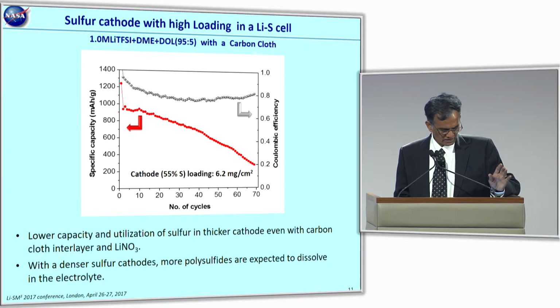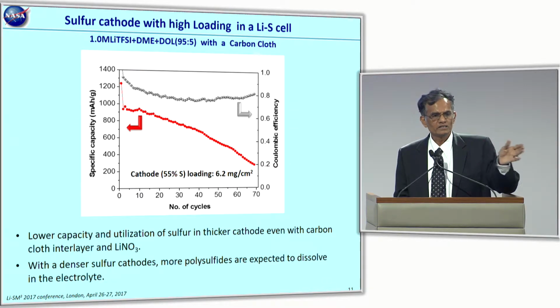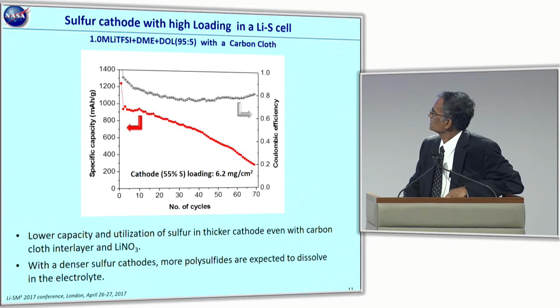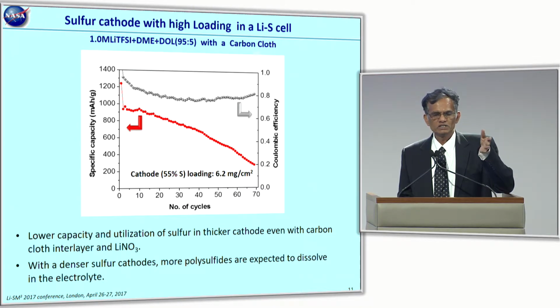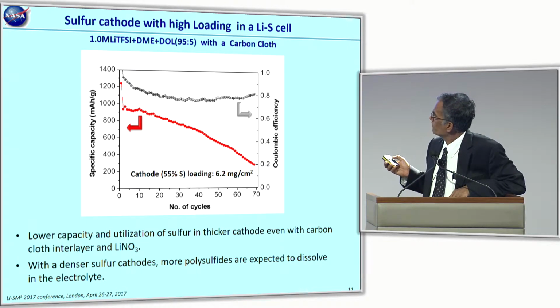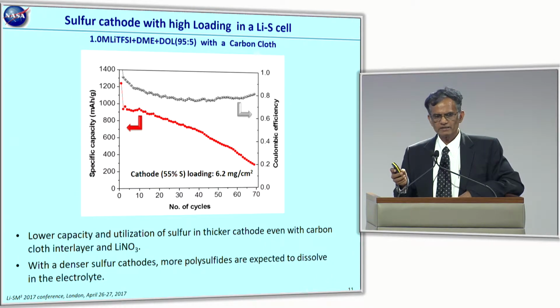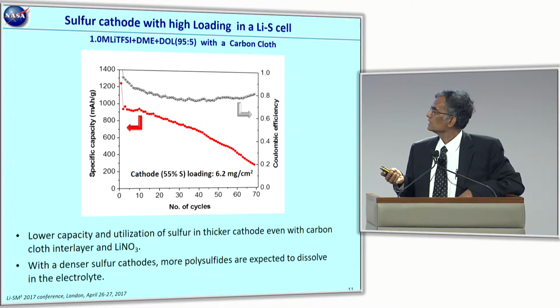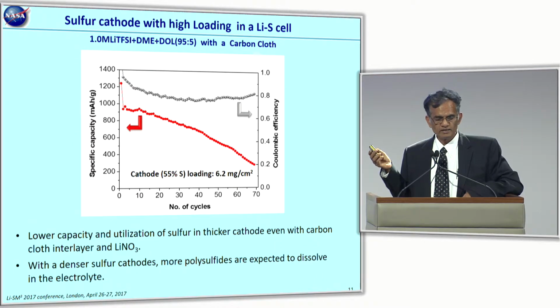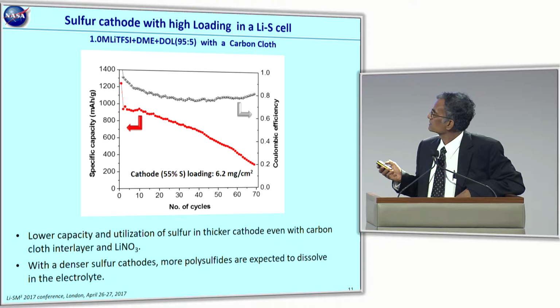And then we determined that we stuck to a carbon interlayer. This is based on the reports from Manthiram, UT Austin. We realized that the presence of a carbon layer between the separator and the cathode seemed to provide us good reproducibility in terms of data. Without that, at least with the loadings that we are dealing with on the sulfur cathode, it was rather difficult to deal with this shuttle. So with a combination of this lithium nitrate and the carbon cloth, instead of a carbon paper, we used a carbon cloth, which is much easier to cut to size. And you still see the fade is not acceptable at this loading, even though we go to like 6.2 milligrams per square centimeter.